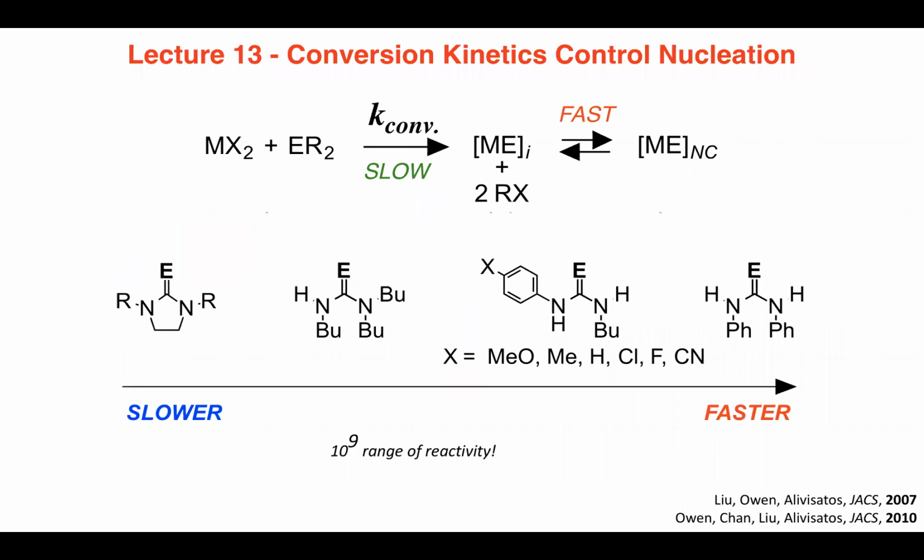And I wanted to show a class of precursors that my group has developed here. Did I mention these ureas and thiourea compounds last time? Yeah. Okay. So these compounds are starting materials that are used to make metal chalcogenides, and they're really powerful because of the relative rates of their conversion reactivity. You get about a factor of 1 billion. It's probably more than that, depending upon what the substituents are, which makes them useful at a variety of temperatures and the typical reactants and so on.